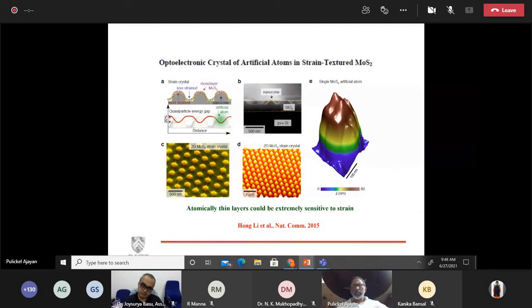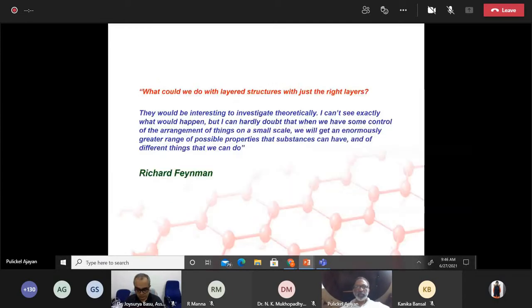So it's really a fascinating perspective on how you can build devices from these nanomaterials, but at the same time, you have this difficulty in really controlling every aspect of its structure. But at the same time, these 2D materials have really gotten a lot of attention in recent times. And again, Feynman was fascinated by these materials because they had this very anisotropic bonding. The in-plane properties are very different from the through-thickness properties.